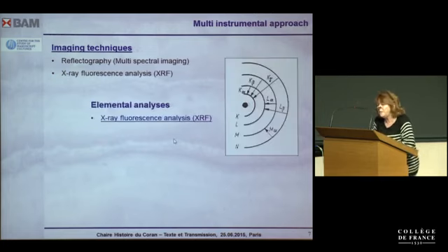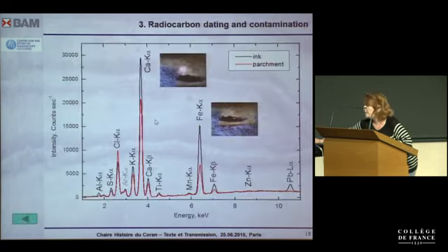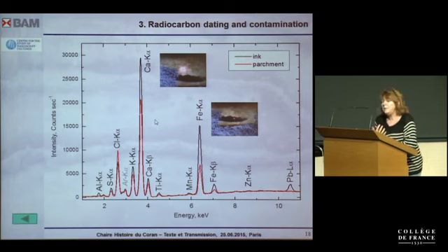X-ray fluorescence. It is a method that everybody uses, and it is based on the fact that you can eject one inner shell electron, produce a hole, then the inner shell will be filled, and the fluorescence is released, which we can detect and write like a spectrum.